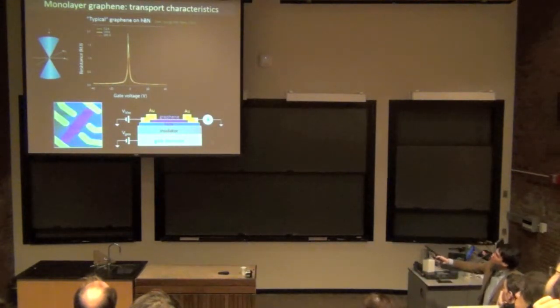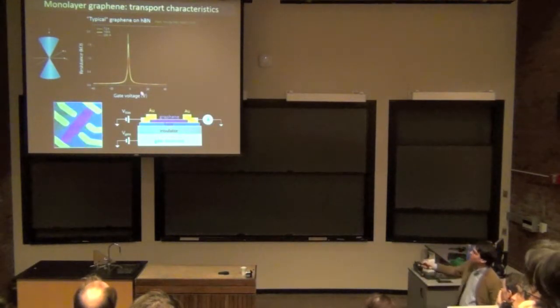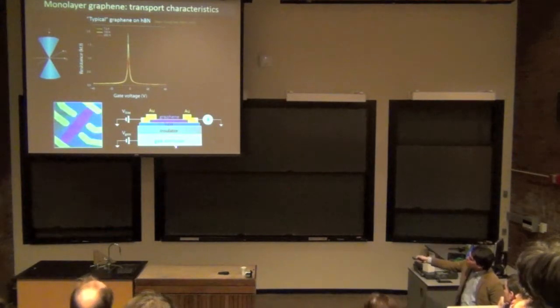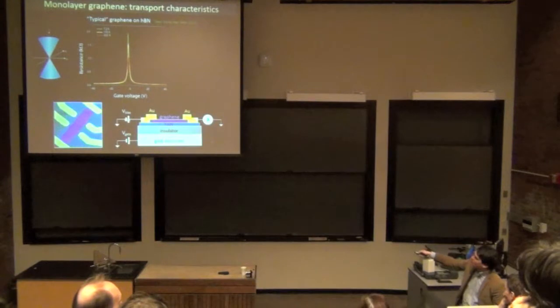And finally, just like you remember this slide, this is essentially what the transport characteristics look like in graphene. So if we fashion graphene into this kind of transport device here, and we measure, say, the resistance of the graphene, what we can do is if we couple it capacitively to a gate, this is just a field effect transistor, we can change the number of electrons in the graphene, and we can actually tune continuously from hole-like conduction to electron-like conduction by means of this gate electrode.